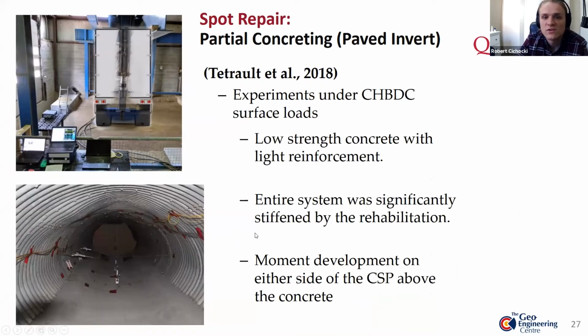So while being tested under these service loads, we saw that this installation actually increased significantly the stiffness of the system. So essentially, we saw a more stiff system after the rehabilitation. Although the concrete experienced bending, it didn't crack under this loading configuration. And ultimately, the ultimate limit state in this configuration was that the corrugated steel pipe was bending.